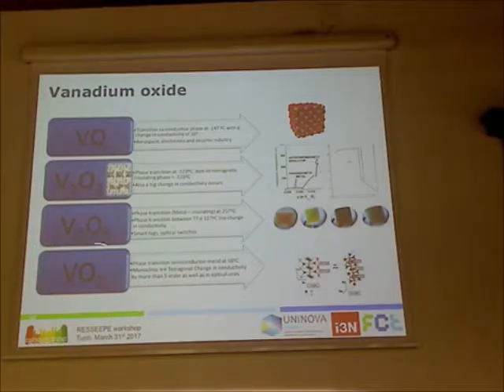And the most interesting phase is VO2, where this phase transition happens at 68 degrees. It's the closest to our room temperature - still very high, but the closest one to room temperature.